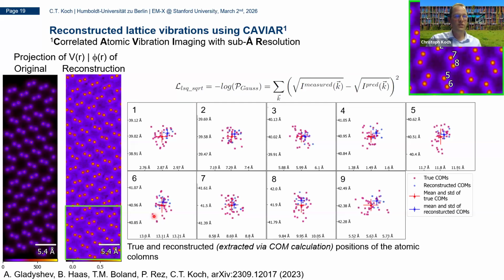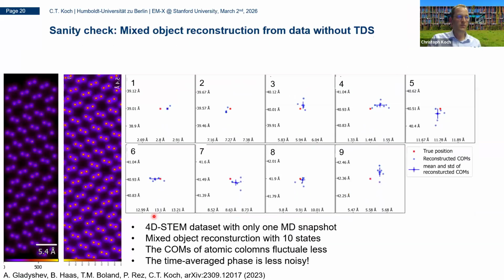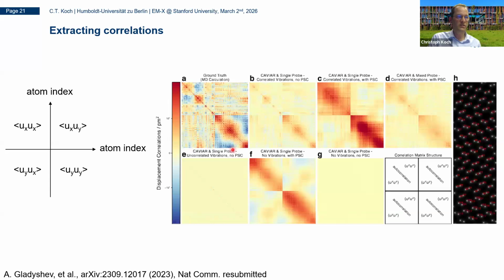But as I will show, you will see that the correlations between the atoms are actually quite correct. And just for a sanity check, if we don't displace the atoms at all, so we don't put thermal diffuse scattering into these simulations, and we go exactly the same reconstruction route to also recover multiple objects, you can see that the displacements in the reconstruction are actually quite small. They're almost negligible, and many of them fall on top of each other. So we really only see these displacements when we have actually thermal diffuse scattering in our diffraction patterns.